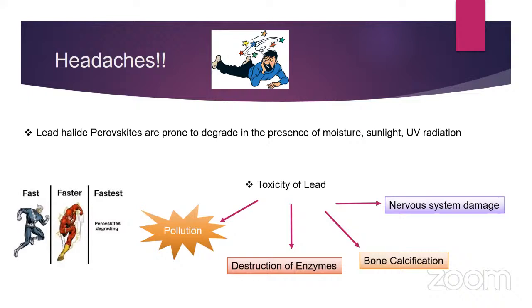And yes, the lead halide perovskite materials are very prone to degrade in the presence of moisture, sunlight, and UV radiation. So in this cartoon, you can see the perovskite decay. It is faster than the speed of flash. And here you can also see that these lead halide perovskites show a decrease in the fluorescence intensity and photoluminescence quantum yield.